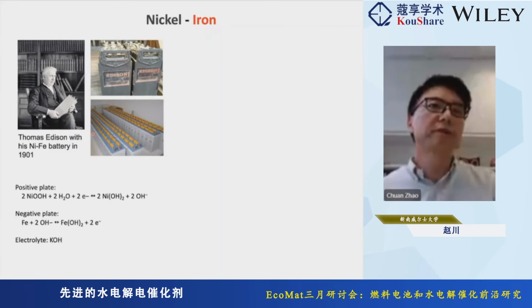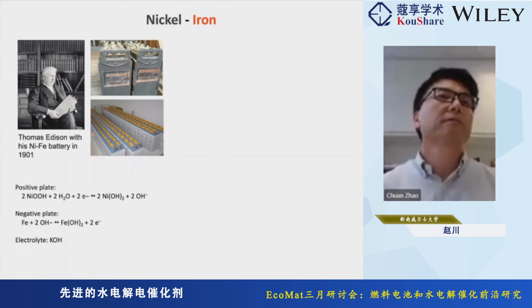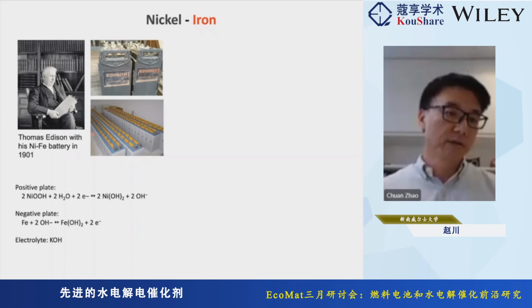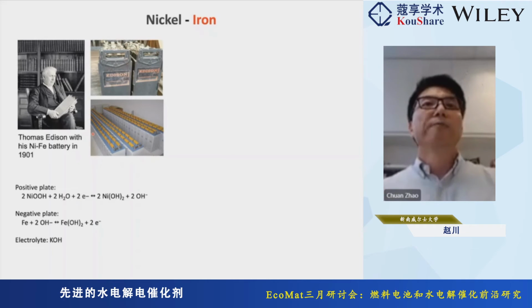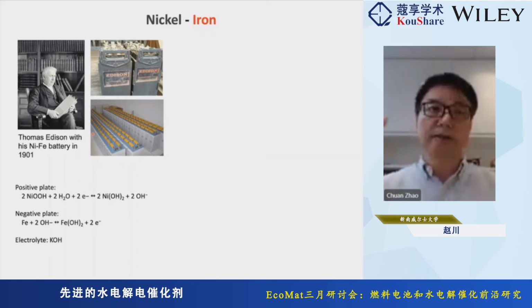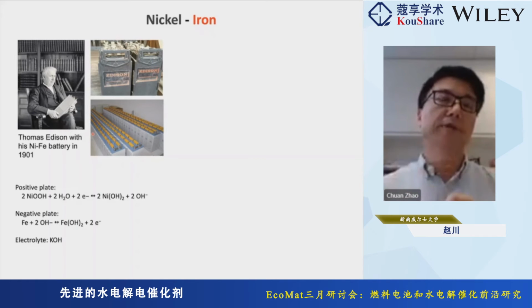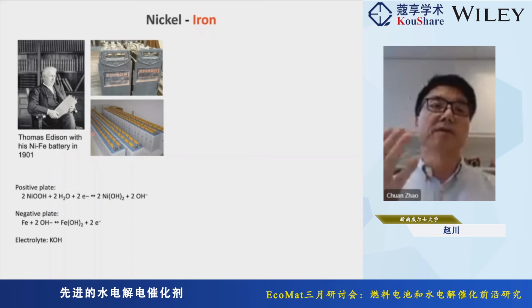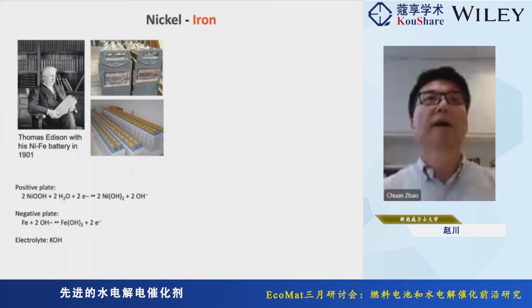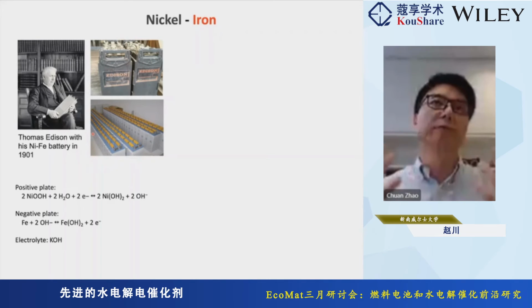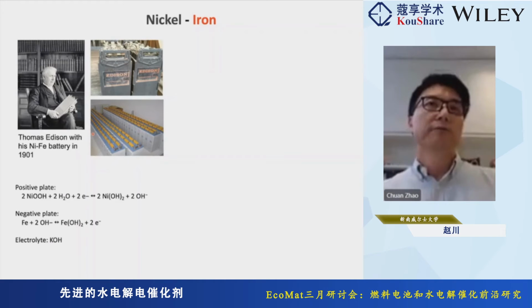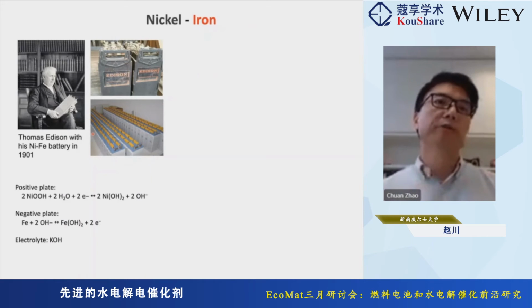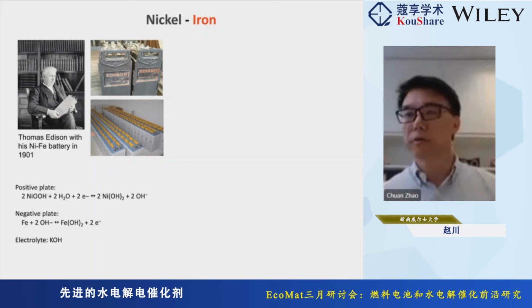But it's actually first known as a problem. When Thomas Edison invented his nickel iron battery in 1901, the battery works in a way that you basically have an iron plate and nickel plate dumped into an electrolyte, which is KOH. What he quickly noticed was that when his positive plate has some iron impurity, sometimes there's a gas evolution inside the battery, and the battery fails very quickly. That's the first time people knew that iron and nickel working together can decompose water very rapidly.